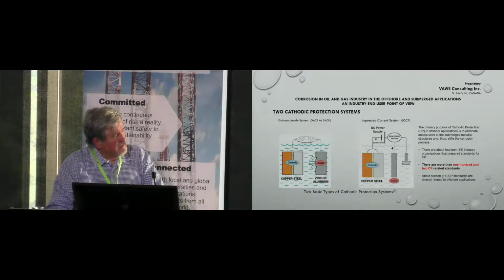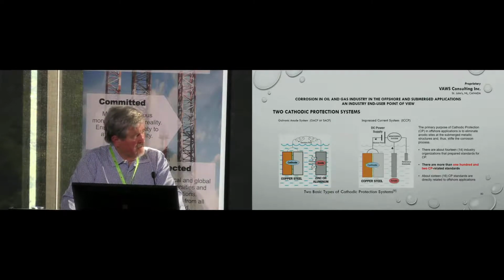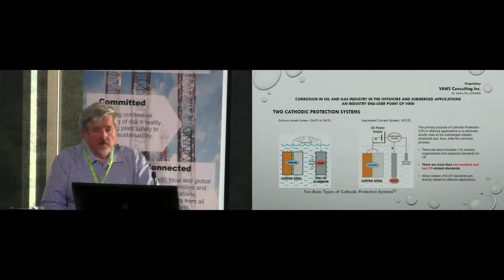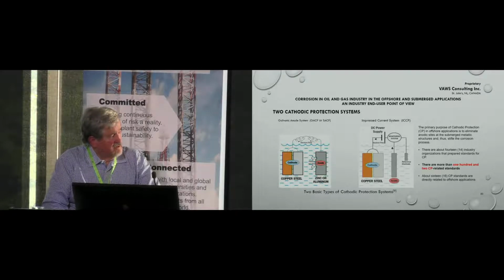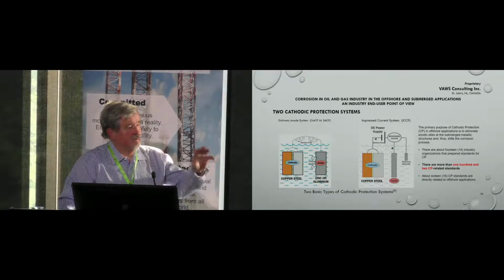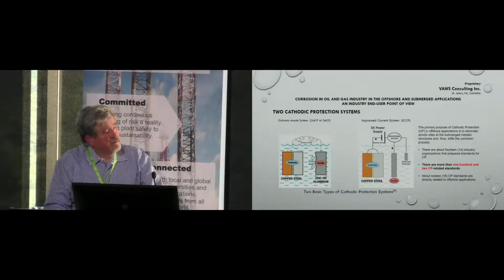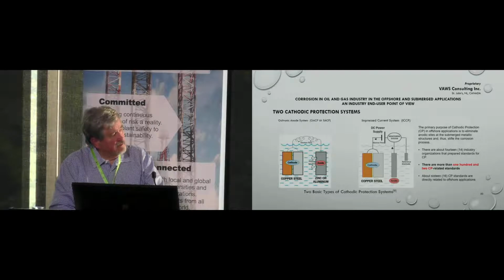Cathodic protection. Cathodic protection is extremely important for offshore operation, and you have basically two types. One is sacrificial, which is the one on the left, and you have impressed current. What you are trying to do is basically overpower the anodic parts on your metal and stop corrosion, because everything has potential big enough so the corrosion is stopped. The sacrificial method is effective, but not for very long distance, because they don't have such an output like the impressed current anodes. You can dial whatever you want on your dial for the impressed current anodes, and the only problem is that if you dial too much, you will generate so much hydrogen, so you will run into another problem, so everything must be balanced. But those are the two principal methods.